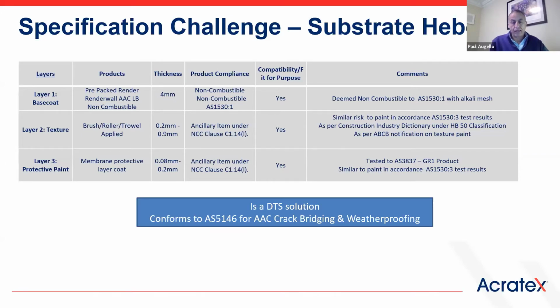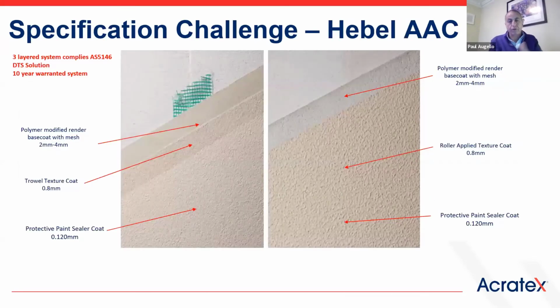So when you put the 3 layers together as a system, which is the way we're generally representing these, it does 2 things in our opinion. A, you've got a deemed to satisfy solution based on how each of the layers can comply, and B, it'll comply to 5146 in relation to weatherproofing and crack bridging as well when you're using this. And primarily, this is what we're looking at here. So if you look at the left-hand side, that is typically what a 3-coat system would look like over AAC with the mesh embodied into it.